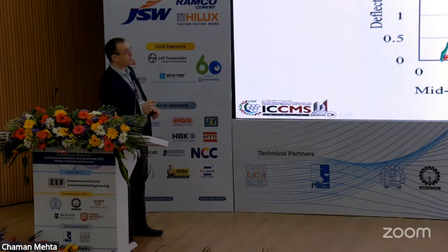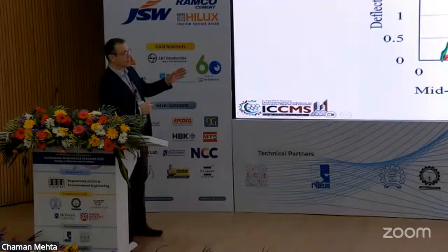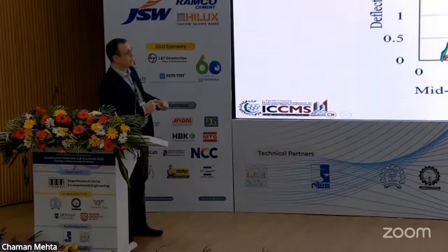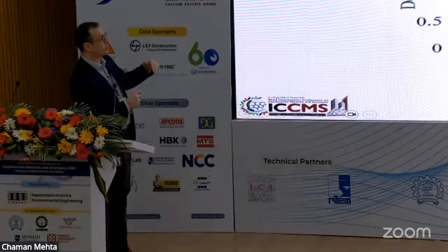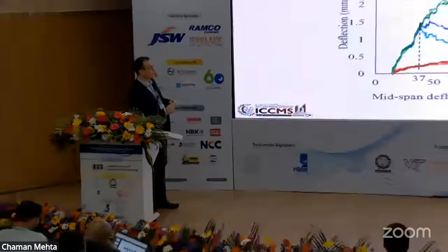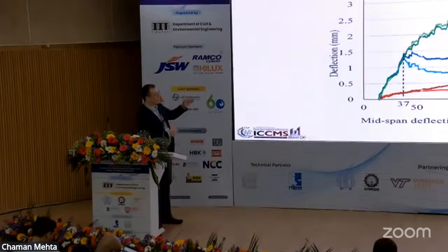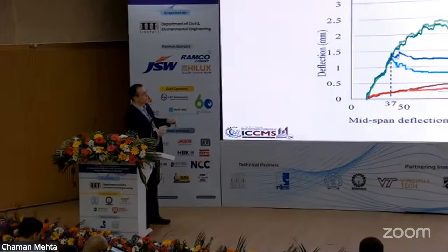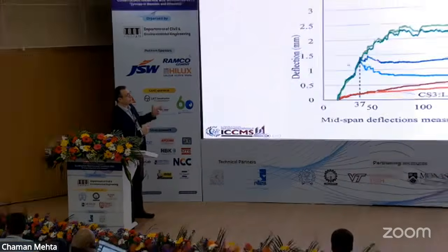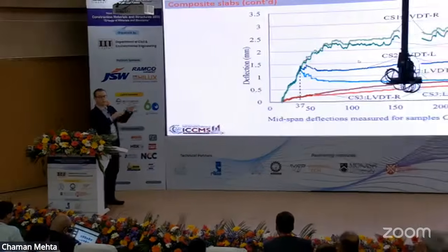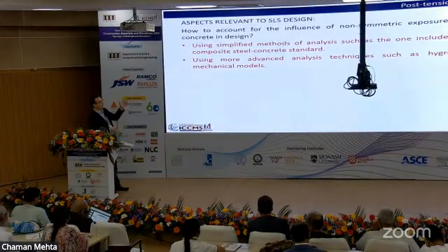We had a similar thing with the continuous samples. And again, these are sealed, the red ones. You got two lines because we got two spans now, it's continuous. And so in this case, you got the two spans, red sealed, green exposed on the top for the entire period. And the blue one is because you seal it after 37 days. The difference is due to cracking already having occurred here a little bit, and therefore the two spans are moving in slightly different ways.